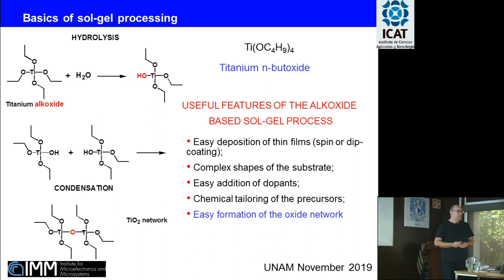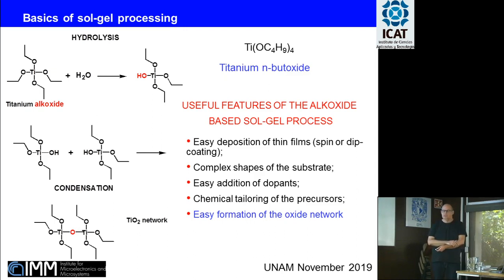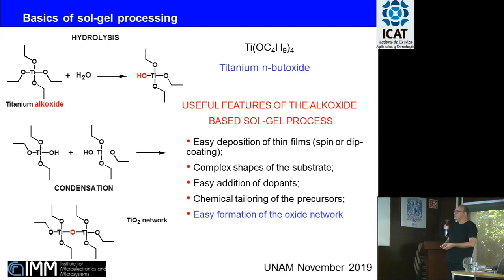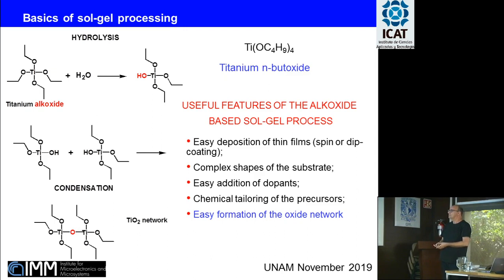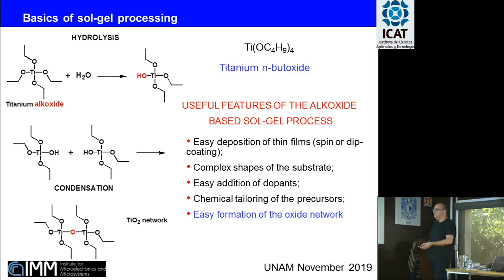In our group, there was already an activity concerning the synthesis of thin films and other materials by the Sol-Gel process. So the first idea was to use the Sol-Gel process to synthesize these thin film materials for gas sensors. I will just give very, very short basics about Sol-Gel processing, since it has become so popular since many years. So basically, the precursor for Sol-Gel process in classical Sol-Gel science is an alkoxide, where a central metal atom is bonded to alkoxy groups, like in titanium butoxide. When this alkoxide reacts with water, with hydrolysis, there is the formation of an OH group. Condensation of two OH groups from two hydrolyzed molecules leads to the formation of an oxide network, which is the advantage of using Sol-Gel process.